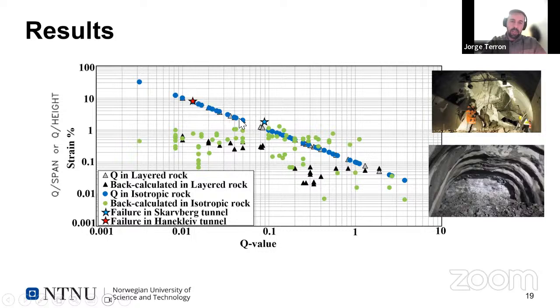Actually, a 10% tunnel strain in a 10-meter span tunnel would be 1 meter of deformation. We very seldom, or I would say almost never, see that deformation in Norwegian tunnels unless you have a tunnel block failure. But then it's a collapse. It's not a plain deformation of the rock mass. So it's a different behavior. So again, from 0.1 to approximately Q value 2 or 3, you have a good match for predicting tunnel strain with the Q value compared to numerical and analytical approaches.